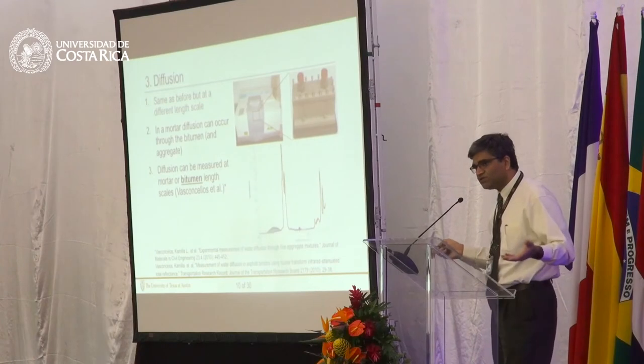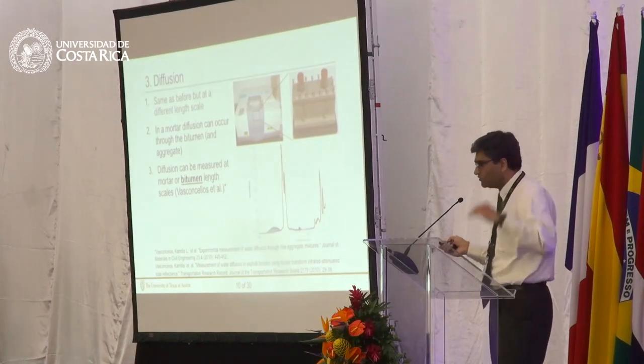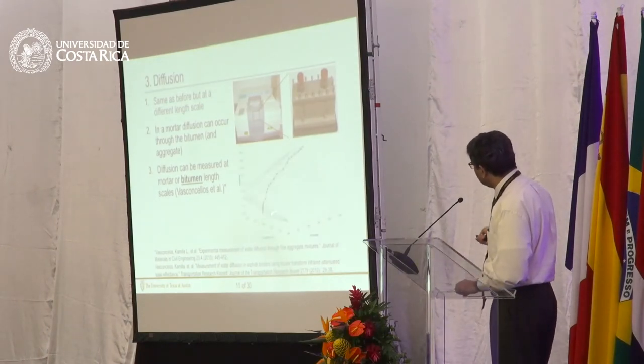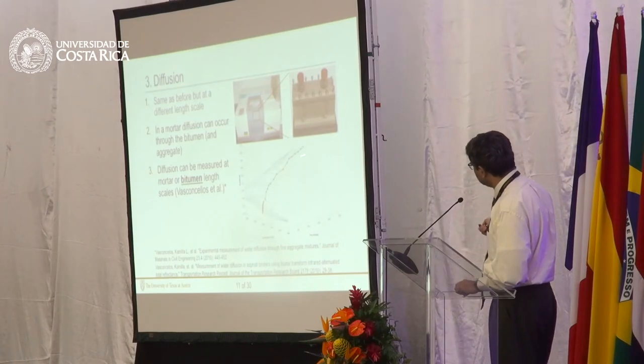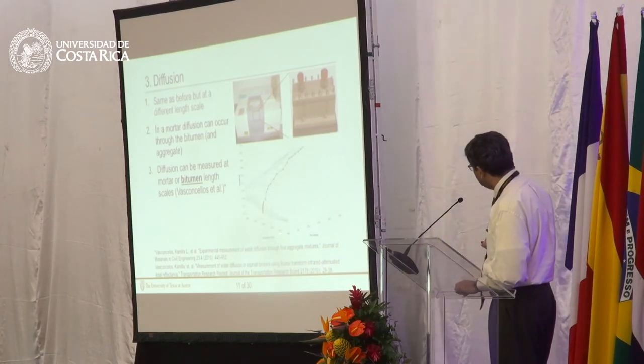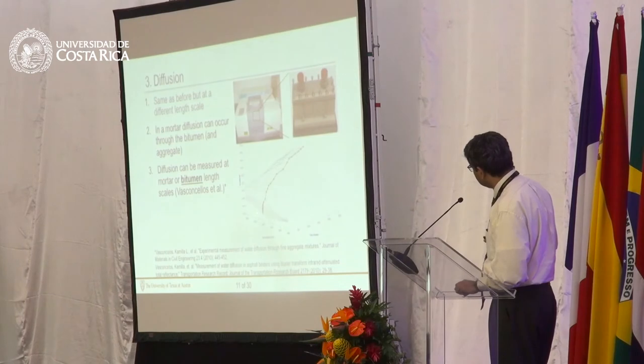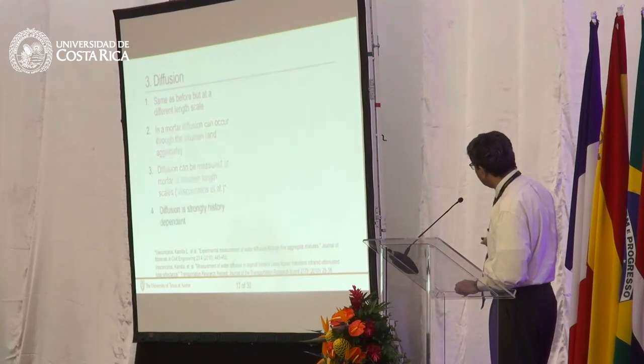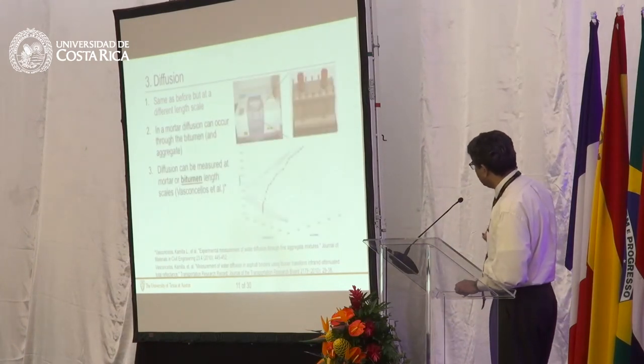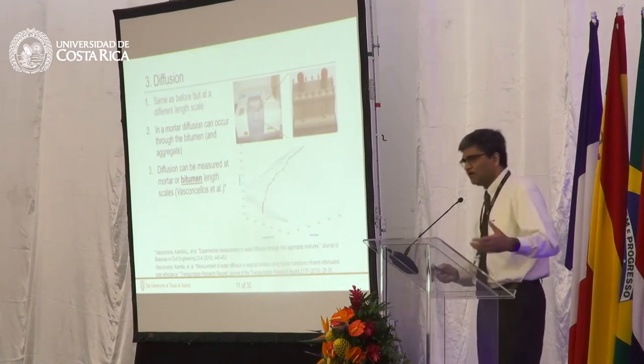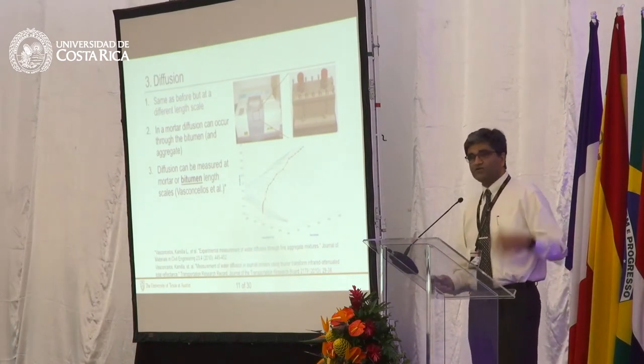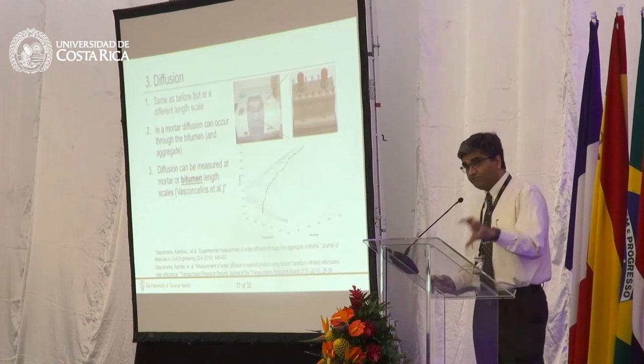So you would soak the specimen and monitor how much the water was traveling into the specimen. And you get this kind of a chart where the peak is increasing with time. This is the intensity. You got the time and you got the wavelength. This is the particular peak that you're tracking. And you do that, and basically you can do the same kind of mathematical calculations as you've done before to calculate diffusivity of binder.